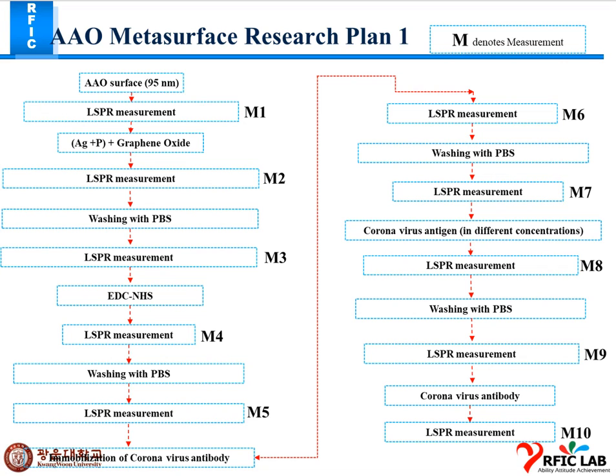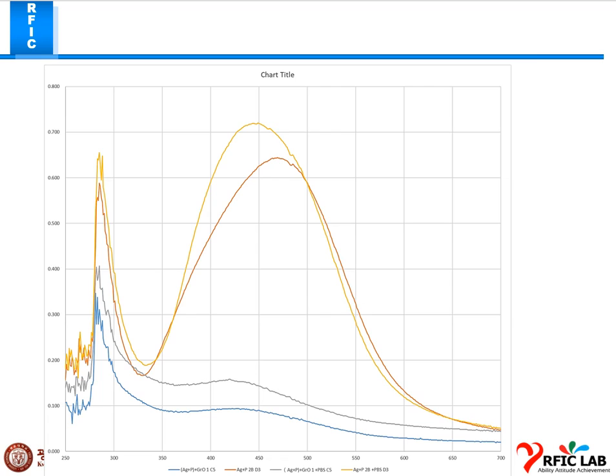And the second plan I have designed. Before I explain the second plan, today we did this experiment. We found that this blue line shows the Ag plus protein and graphene oxide mixing solution, and then we checked the LSPR. We found a peak nearby 420 wavelength here, and the same after washing with the PBS.